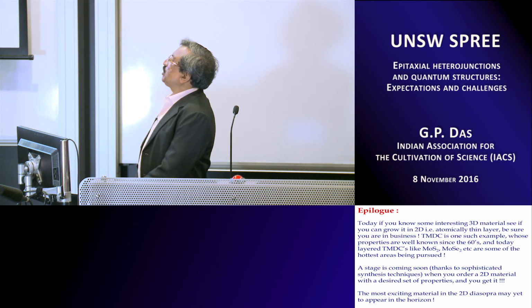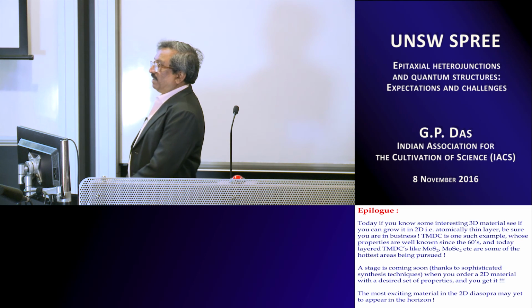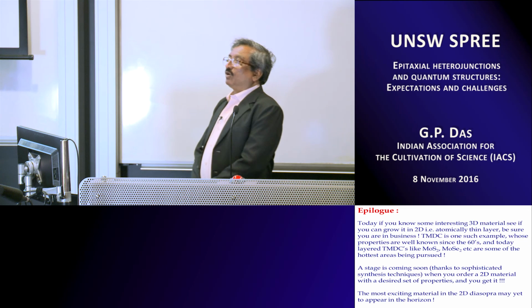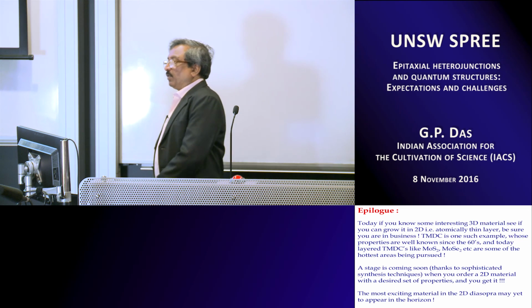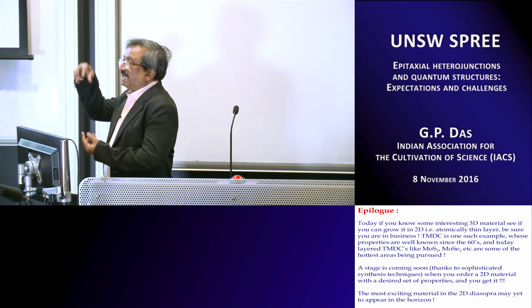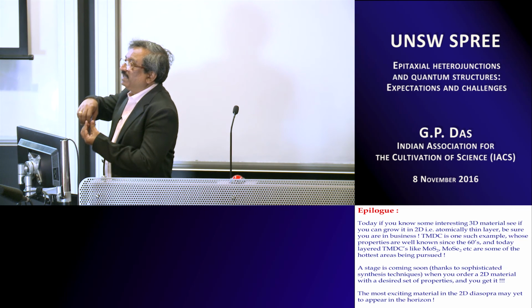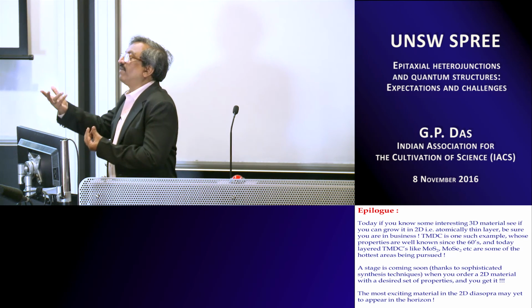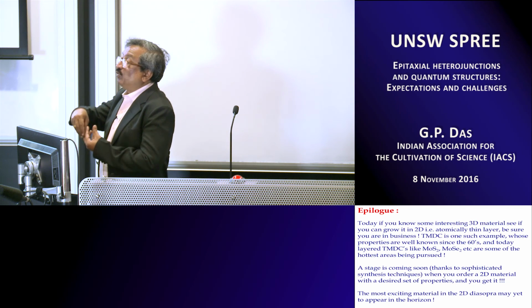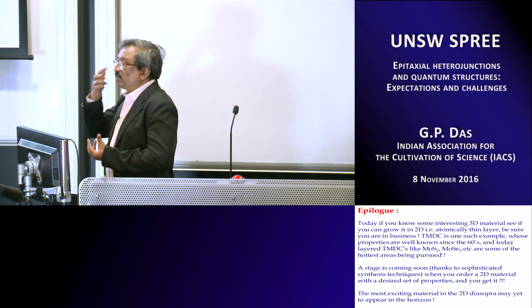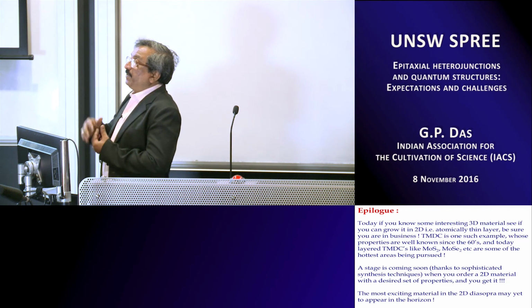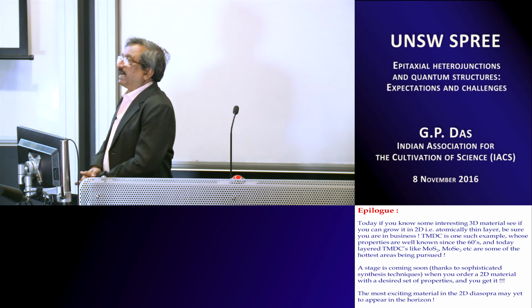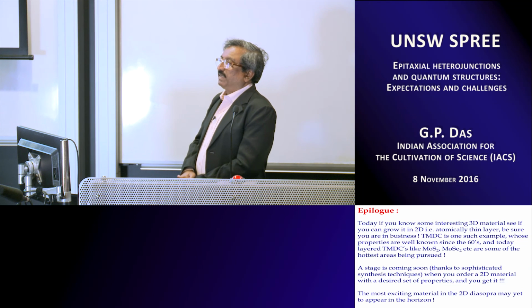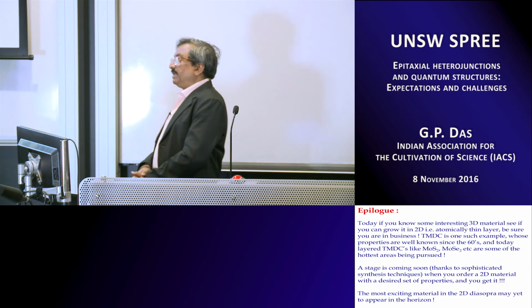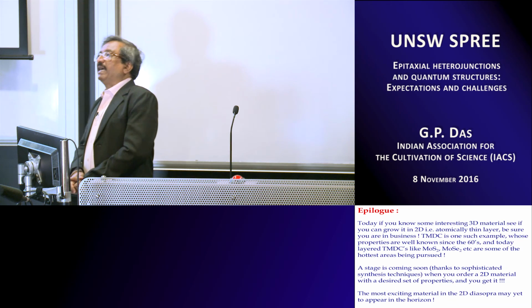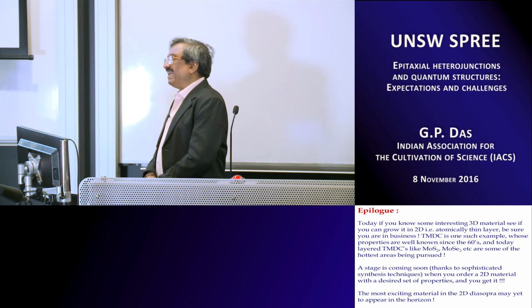historically speaking, most of the experiments which I pointed out have been done on silicon 111, and the reason is simply the following. In case of the nickel disilicide example which I gave you, the lattice matching is exact, almost 0.5%, almost 0, between NiSi2, which is a calcium difluoride, CaF2 structure, and silicon 111. And to the best of my knowledge, the X-ray standing wave experiments that were done in Hamburg, at DESY, the Deutsches Elektronen-Synchrotron, were done on silicon 111, not 100.